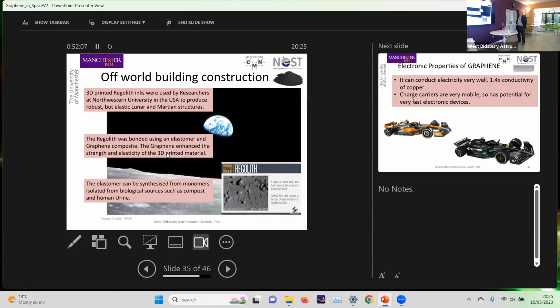And the idea is that you have to use materials that you have available rather than take them with you. So you might take a 3D printer, for example, but these people have shown that if you mix together this regolith with an elastomer and graphene, then the graphene strengthens it enough, makes it flexible enough, so that you could actually make structures. And this elastomer can be obtained from biological sources like compost and urine and so on. So you're essentially being able to generate the material which you're going to use for constructing your buildings and so on, actually on the planet.